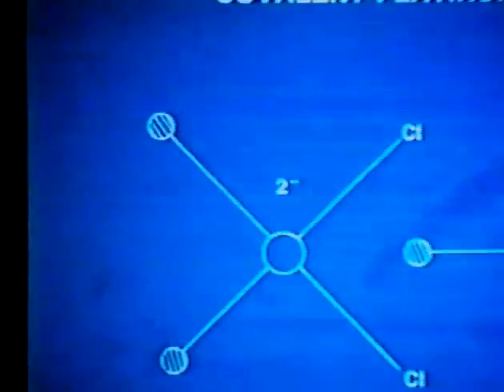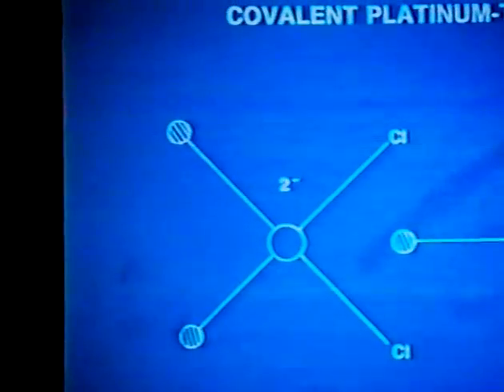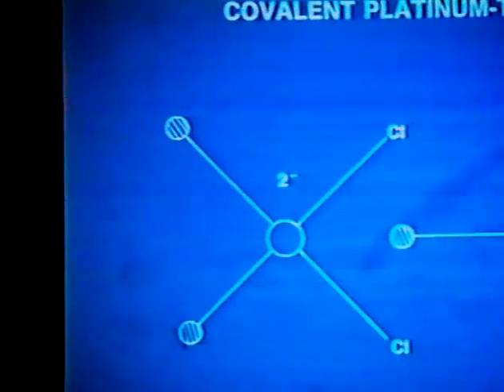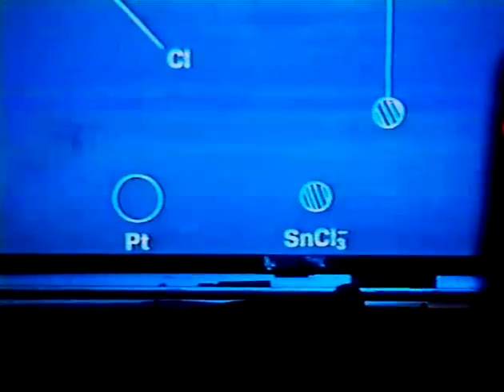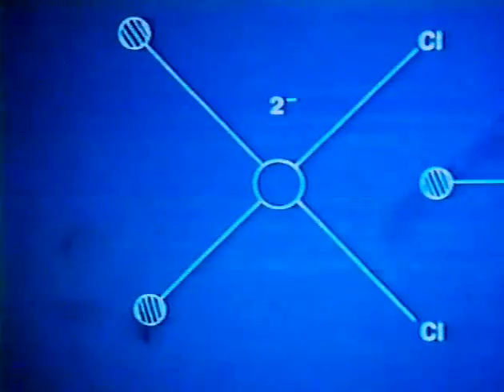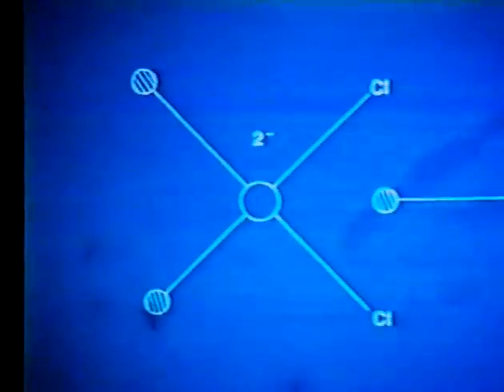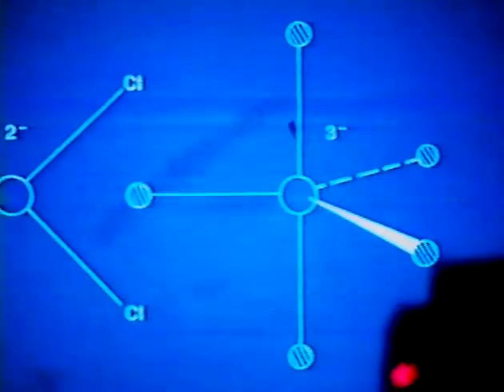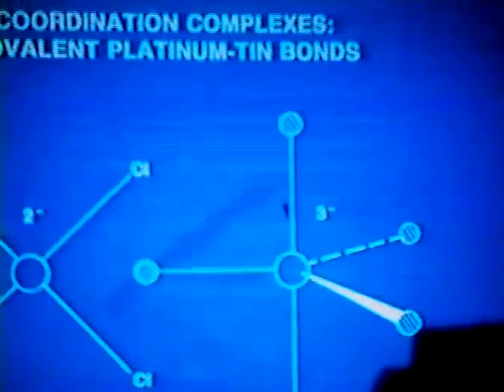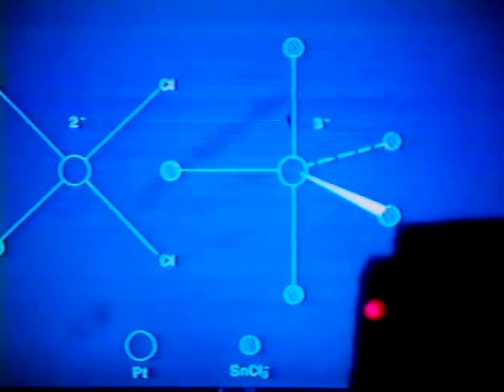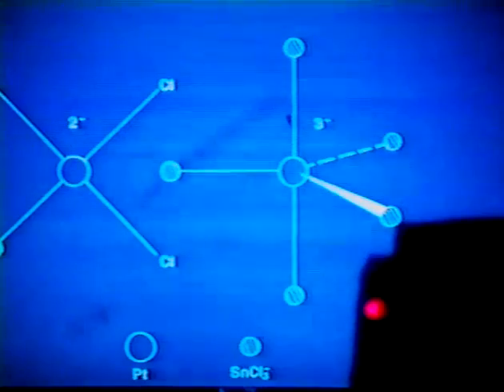All right. Concerning platinum tin catalysts, which I think are the more interesting of the lot. This is a sort of a coarse model for the interaction that I am claiming goes on in those types of catalysts. There is unambiguously an interaction between platinum and tin, and the tin is substantially 2+, not tin-0. They're not really bimetallic catalysts at all. They're platinum on a modified support.